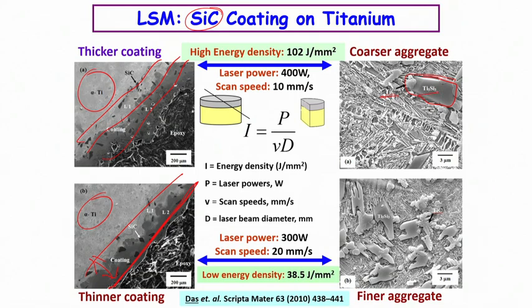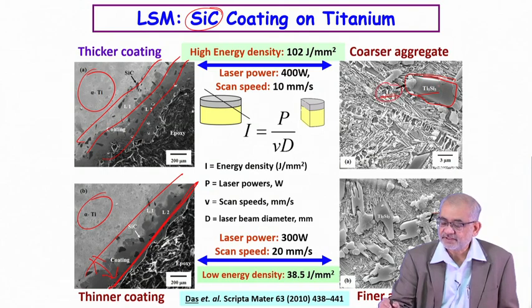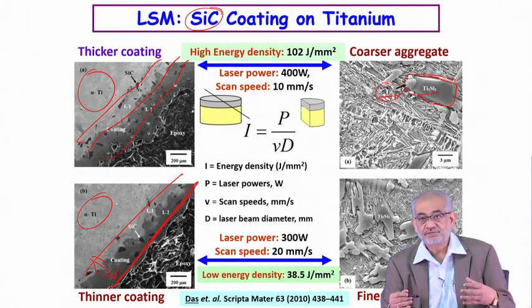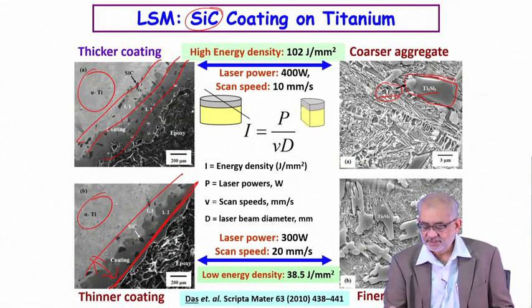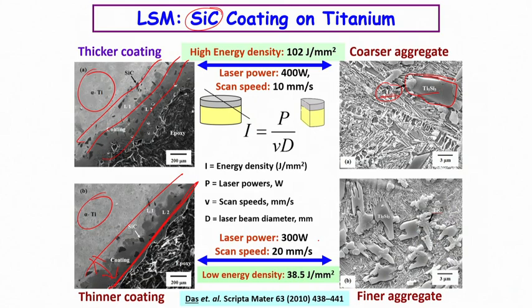So now you are seeing a microstructure which comprises carbides and silicides both, but you applied only silicon carbide. So the silicon carbide, during the laser assisted surface engineering process, intermixes and then creates these kinds of combinations of carbides and silicides. So in a laser assisted process, you are able to develop a composite layer onto the surface, which otherwise is not possible by simple deposition techniques. And the fineness of the aggregate, the microstructure, makes this whole coating much tougher and much more adherent.